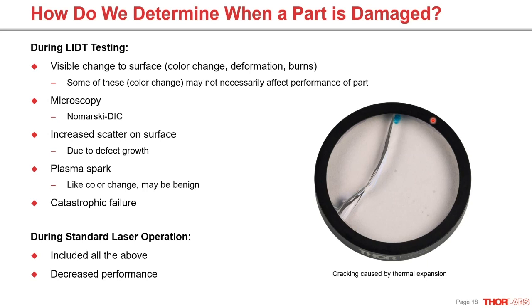And of course, you can sometimes see catastrophic failure. In the case of this, it wouldn't surprise me if you could hear catastrophic failure. That's one other thing to keep an eye out for. If you're not damage testing, if you're just operating a laser or a laser system, and you see any of these, that should put you on alert or decrease performance. If you suddenly see, I had this nice system putting out a good looking Gaussian beam, and then suddenly your beam starts looking a little deformed, or you start losing significant power, you may have an issue like this. So that's something to keep in mind.